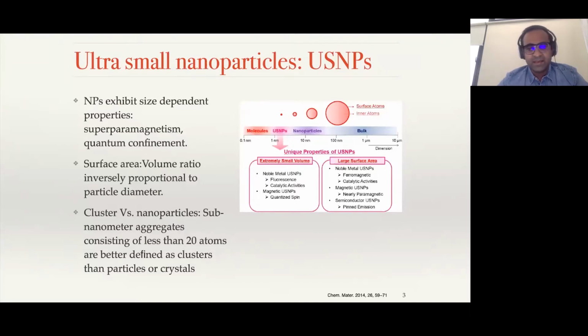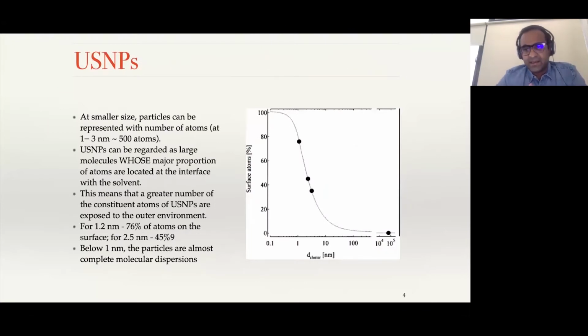Well, in the next slide, we'll see the answer to that. If you look at this slide, it basically tells you a plot between the diameter on my x-axis and the percentage of atoms on the surface on my y-axis. Now, what it tells me is that if my particles are getting smaller and smaller, the proportion of atoms which are at the surface becomes higher. In other words, most of my atoms which are contributing are at the surface if I reduce my size.